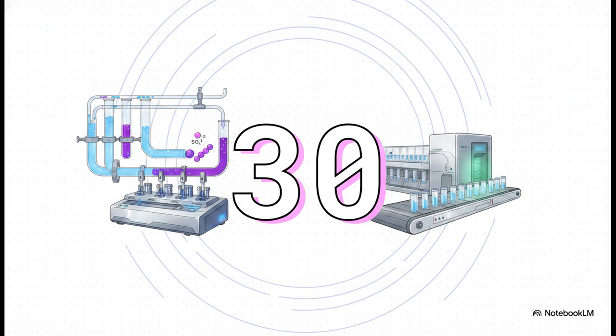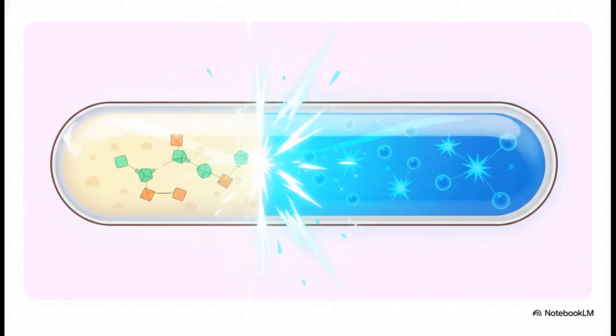It's an absolute powerhouse for large-scale environmental monitoring. This high-speed method uses a really clever two-step pH shift right inside the machine's tubing. First, the sample hits a low pH environment with barium chloride, forming our familiar barium sulfate. But then, the machine instantly shoots in sodium hydroxide to spike the pH. At this high pH, any leftover barium that didn't find a sulfate partner immediately reacts with a chemical called methylthymol blue, and that reaction produces a super vibrant blue chelate.